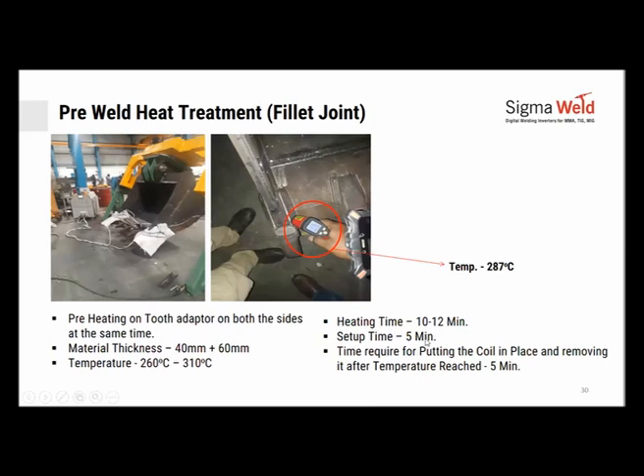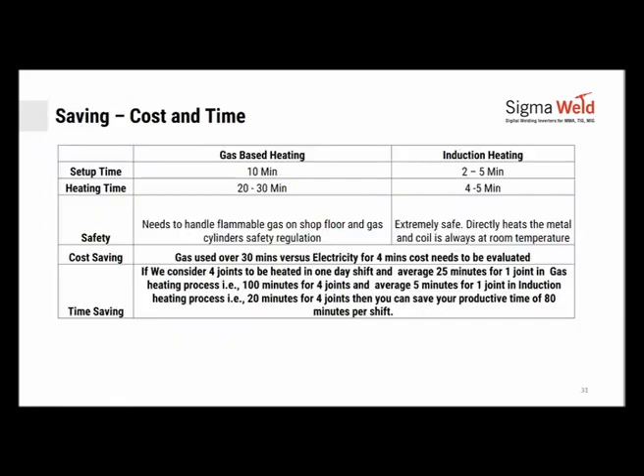Setup time under 5 minutes, 10 minutes to begin with. Again, 20 minutes, your job is out. Time taken to require to put the coil in place, to remove and start welding, under 5 minutes. You see, if you were to do gas-based heating, 10 minutes would be setup time. In induction, 2 to 5 minutes setup time. Heating time, 20 to 30 minutes in a gas-based system, whereas 4 to 5 minutes on the induction heater.